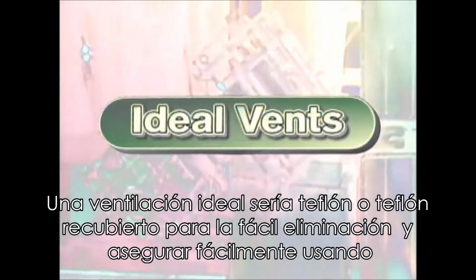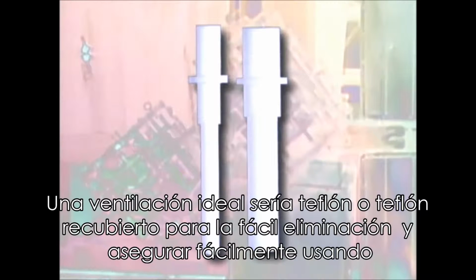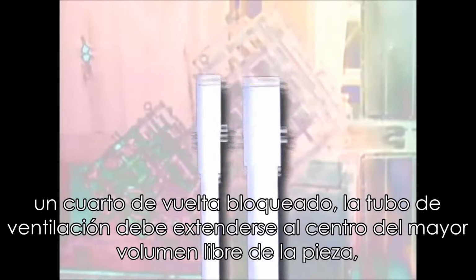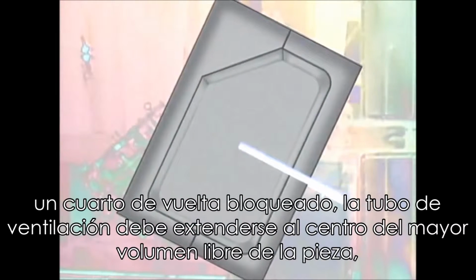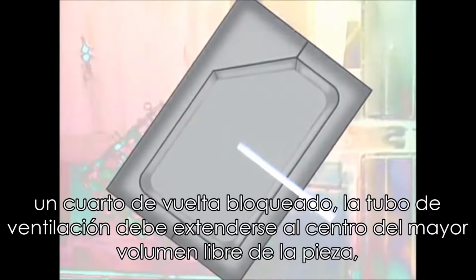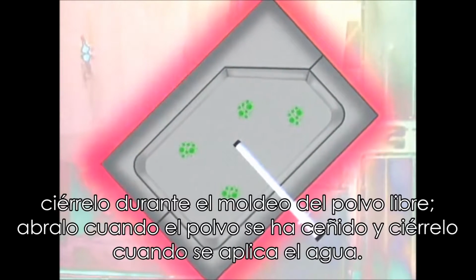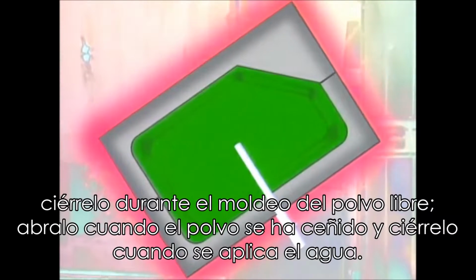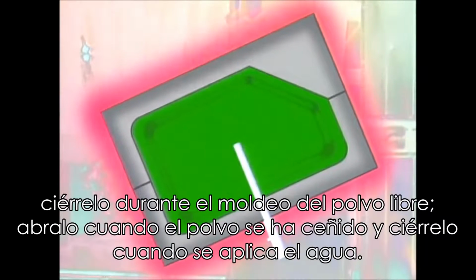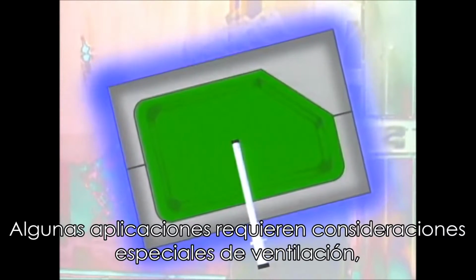An ideal vent would be Teflon or Teflon coated, tapered for easy part removal, and easily secured using quarter-turn locking. The vent should extend to the center of the largest free volume of the part. Close during molding of free powder. Open when the powder has adhered, and close when water is applied.